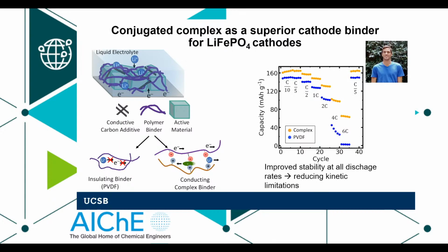We're comparing the blue, which was the data I showed you earlier of just the PVDF type binder, with that conjugated polymer binder. And you're seeing that at all rates, we have much, much higher capacity when we use the conductive binder. And also that it's reversible. If we go to a very high rate, like 6 charges and discharges per hour, then we go back to a slow rate, we're able to recreate things. And so we've got a very, very stable binder that doesn't seem to degrade with operation.